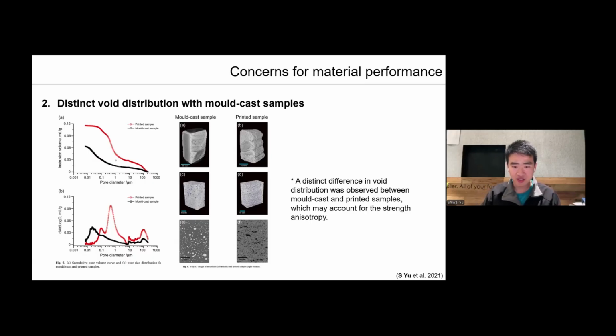We also observe a distinct difference in void distribution between cast and printed samples. In cast concrete, pores are mostly round in shape, while in the printed concrete, pores are often elongated or directional, a result of the pumping and extrusion process. So this difference in pore distribution is the main contributor to the anisotropy of the strength.